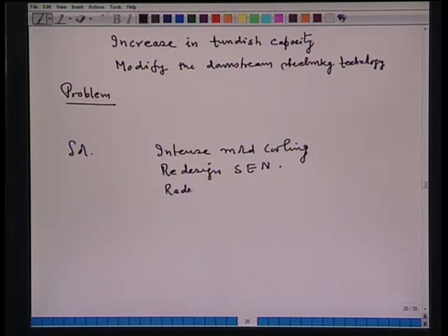So, accordingly, you have to redesign the fluxes, so that they can melt at the rate at which the partially solidified strand is withdrawn from the mold. A mismatch between the two will cause or may cause the air gap formation or increased amount of friction between the mold and the partially solidified strand. So, these are the issues. Now, okay, you solve these particular issues.